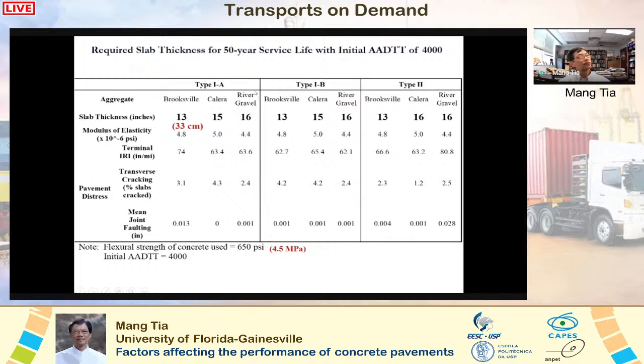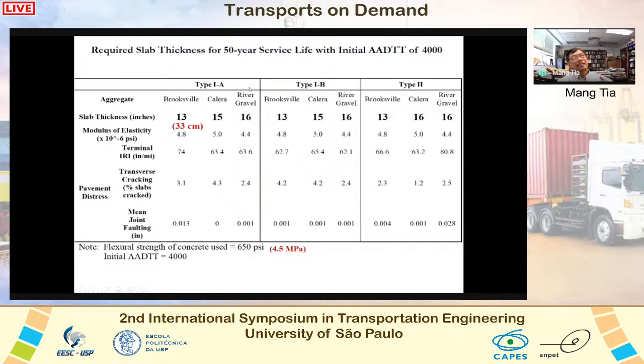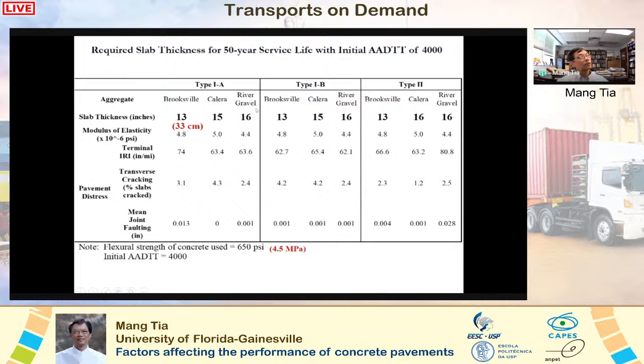But if we use river gravel, the concrete is as strong as the other one, but because it has a high coefficient of thermal expansion, and also a relatively higher elastic modulus, the performance is not as good, and we would need 16 inches versus 13 inches. The results are similar for the other designs. The key thing here is to use the right aggregate. It's not the strength, it's the aggregate.